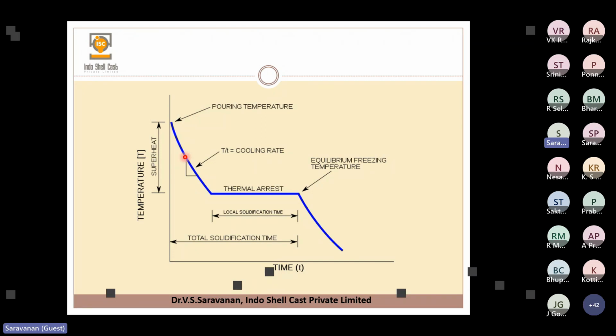So theoretically, 1140 plus 200 degrees centigrade, the excess metal plus 80 degrees, maybe 1300, 1400 degrees is sufficient. But because of the pouring constraints, we are actually heating the metal up to 1500 degrees. Even sometimes some foundries, having very small pouring weight and more number of molds, are going up to even 1550, 1560, even for the cast iron.